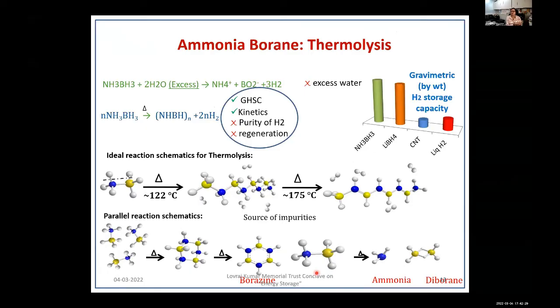The other class is chemical hydrides, which store much more hydrogen than conventional materials, whether it is a physical form of hydrogen like liquid hydrogen, or the adsorption way of storing hydrogen, such as carbon nanotubes. So the quantity of storage is very high. Here we talk about 19.6 weight% as against 2 weight% in the case of metal hydrides. But if it were so straightforward, then we would have found the solution. There are still disadvantages: the hydrogen which we are getting is not pure, and the problem lies with the regeneration of these materials.